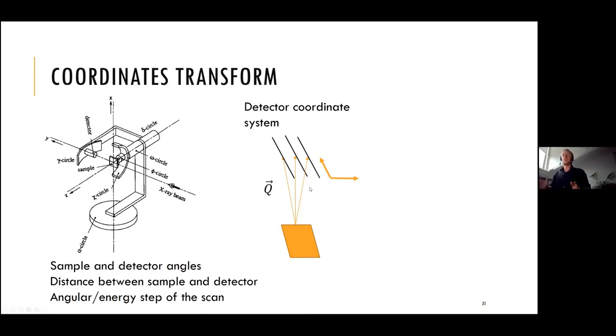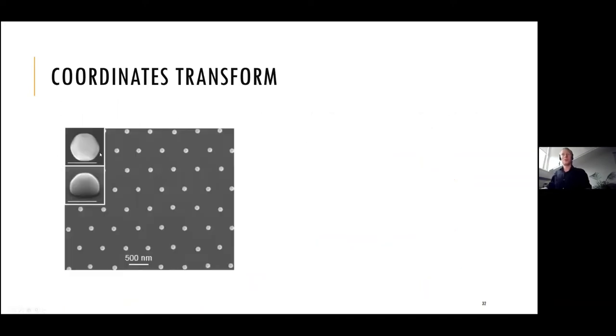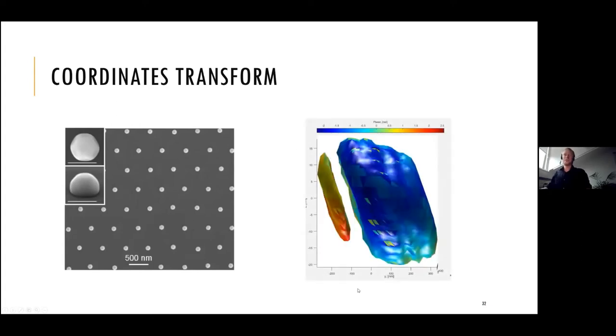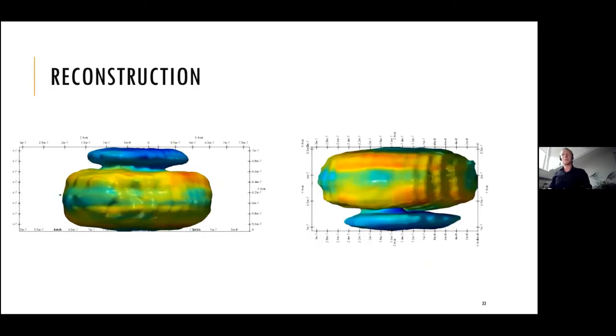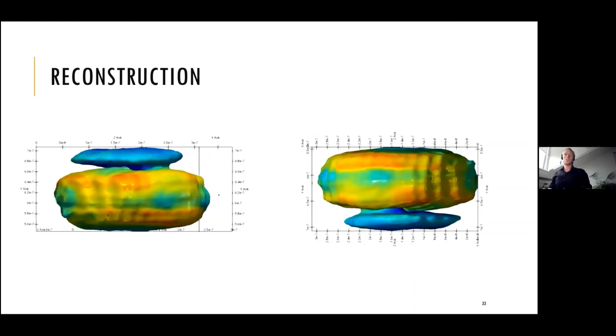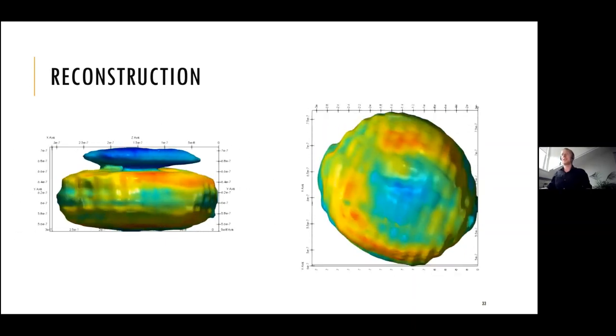So basically, your object is skewed, but after resampling towards the lab coordinate system, it becomes orthogonal, and it's much easier to work with because we work with matrices in this technique. As an example, the gold nanoparticles normally look like that, very symmetric with a nice shape, but in a skewed coordinate system, it looks something like that. This is a reconstruction of the data from before. But after the remapping towards the lab coordinate system, it becomes more symmetric